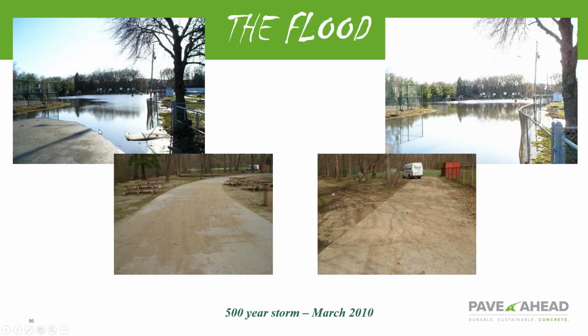And if you see this here, that park I showed you was way behind those basketball courts. It was underwater for almost a month. And when the water receded, the entire pervious concrete system was plugged up with Passaic River muck. And if you ever watch The Sopranos, you kind of know what would be in the Passaic River. They power washed the entire park and got it to drain again. Worked very well with just the power washing.